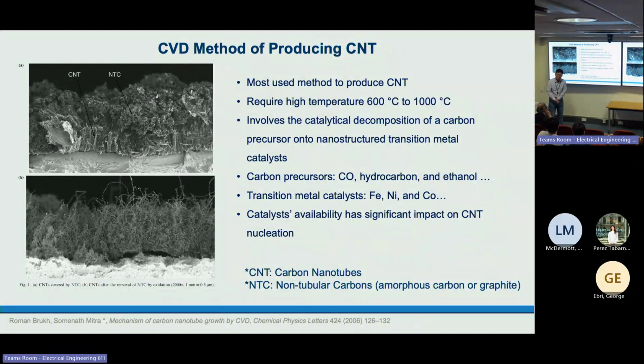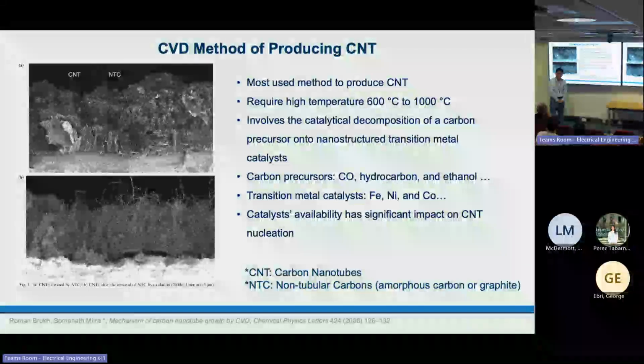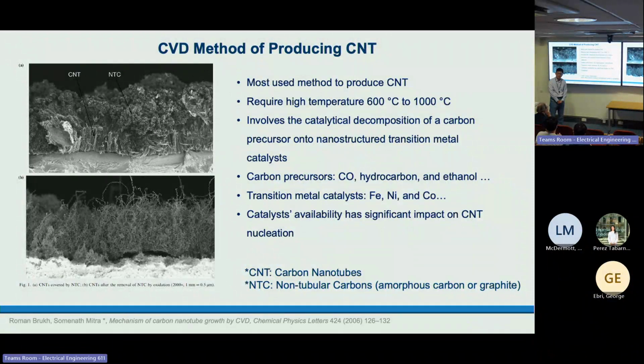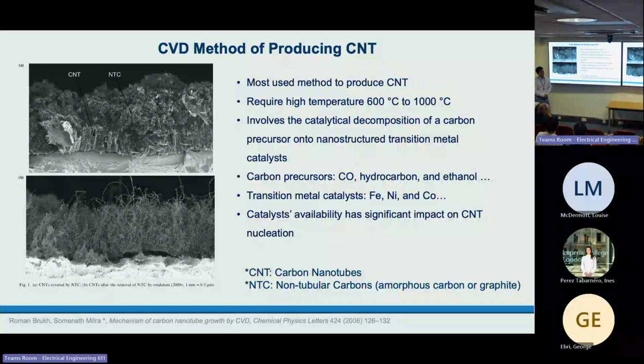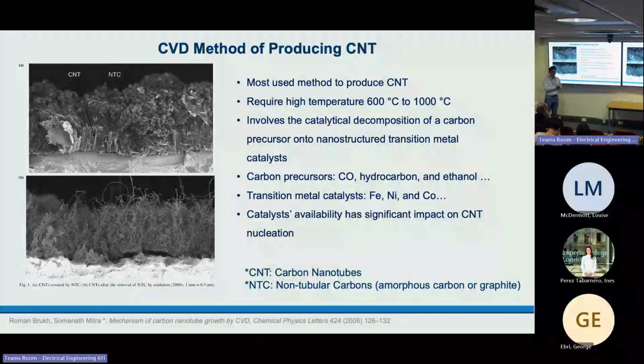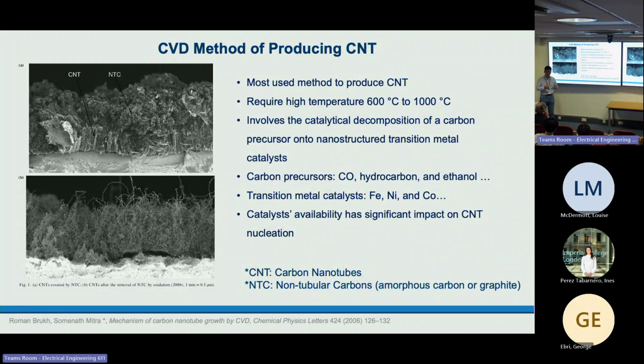When you change the actual materials and it gives you different carbon materials, have you got any idea how the material affects the morphology of the carbon materials? Yes, this is my hypothesis. The method to produce carbon nanotubes in molten salts, I think the mechanism should be similar to the CVD method. For the CVD method, they heat up the substrate, for example iron, to high temperature in oxygen, so part of the surface of the iron substrate gets oxidized, and then they use hydrogen gas in the hot chamber to reduce the iron oxide back to iron again. In that case, the substrate will be iron nanostructures.